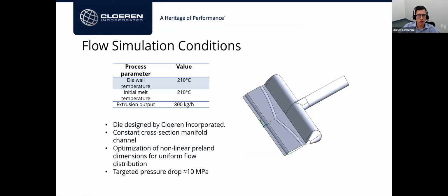From that, we design a die based on not only the viscosity measurements, but also the process information given by the customer. So the melt temperature will be set at 210 C, extrusion output is 800 kilos per hour, and we design the die, optimize the flow channel, like mentioned, with the 3 main parameters, which are uniform flow distribution, a pressure drop, which makes sense. In this case, we're targeting 10 megapascal or 100 bars. And of course, we want a residence time that makes sense with the temperature, with the material sensitivity. These materials seem to be fairly good, actually.